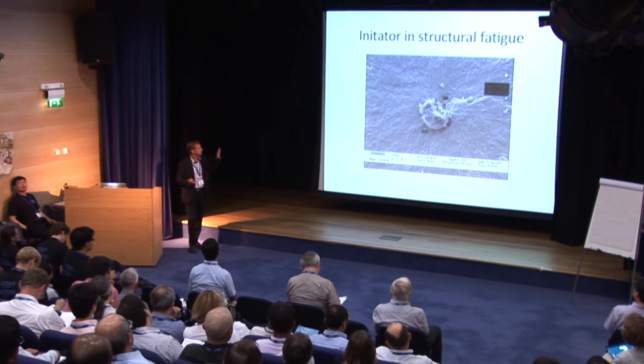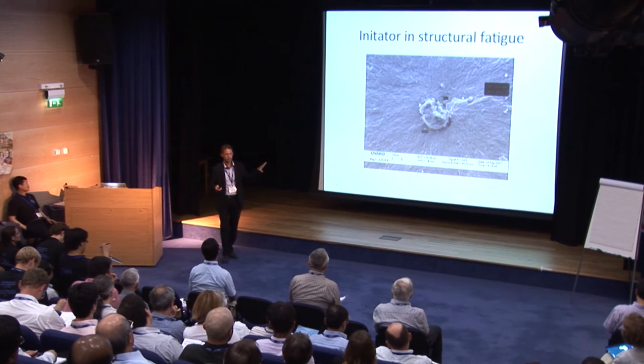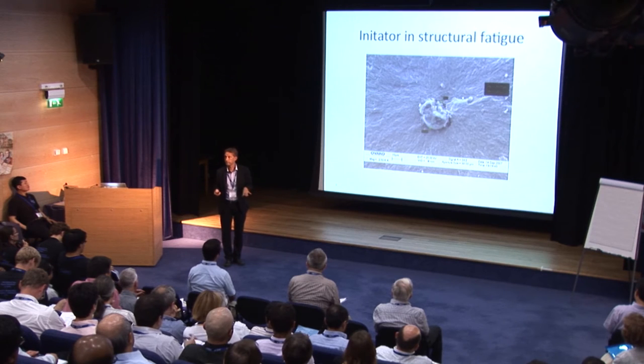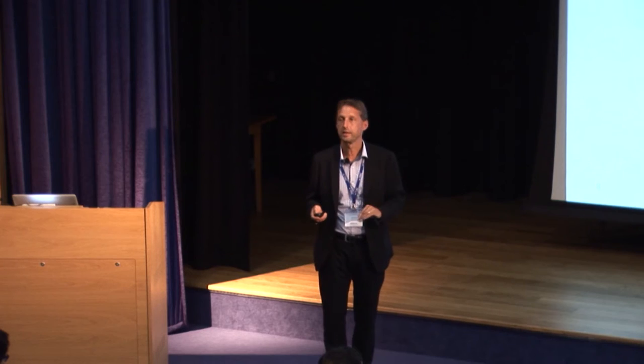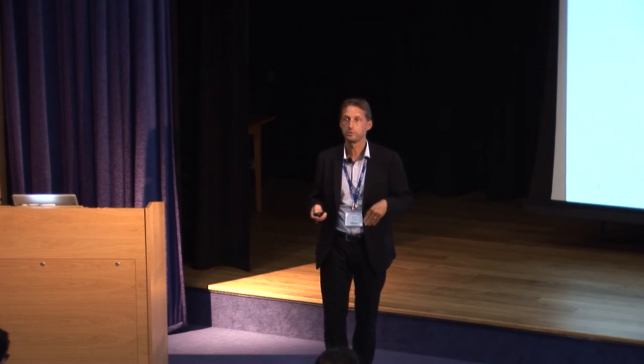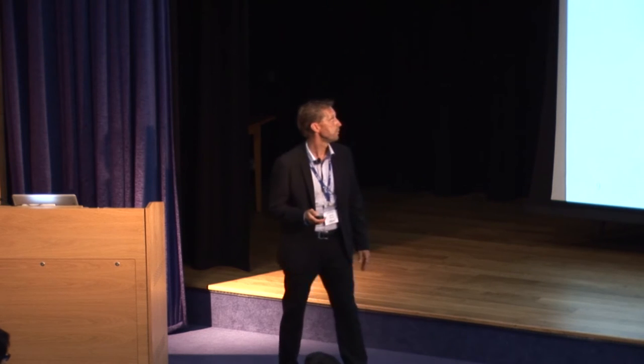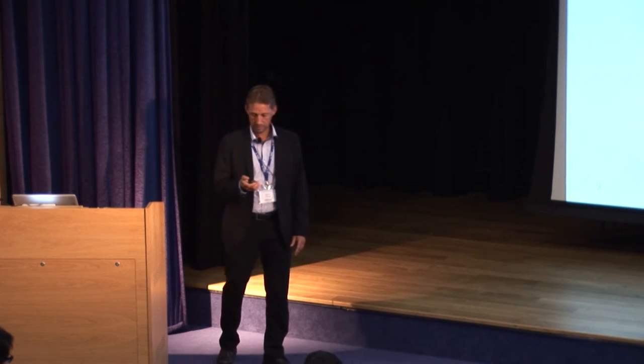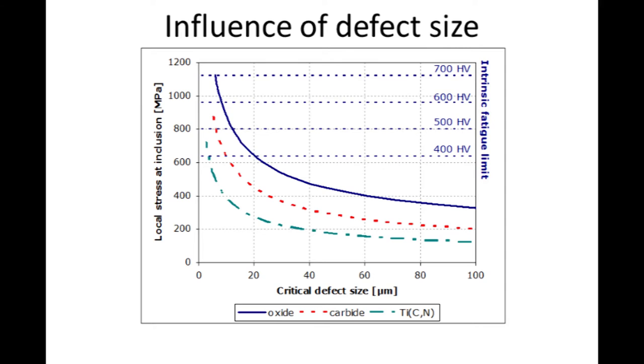We did a lot of testing when it comes to fatigue, especially rotating bending fatigue, because it's a fairly simple way of producing samples. You can generate a lot of data in a short time. And this is one thing that we came up with, which supports the Murakami theory: the larger the defect, the more detrimental for fatigue. And it works quite well.